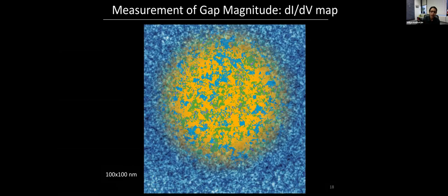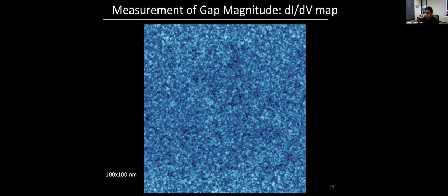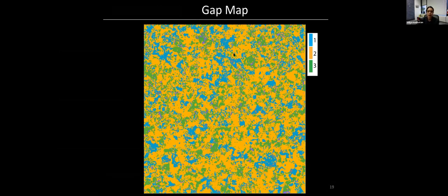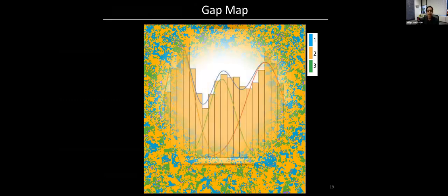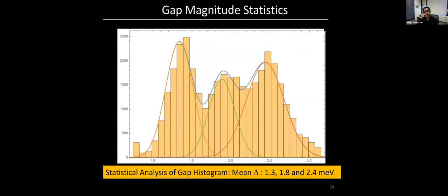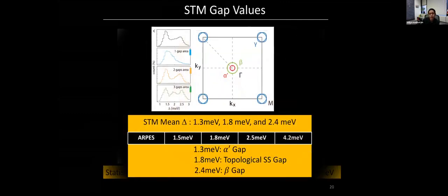And so we can go and measure the gap at each position. And as usual, this is what I would call a gap map. But the most important thing here is that there are regions here where you see 3 distinct gaps. And if I do a gap histogram, this is a statistical analysis from thousands and thousands of spectra, then you can see that we do have 3 distinct gaps, although the histograms are broad because of inhomogeneity. The gap values have mean values of 1.3, 1.8, and 2.4 meV.